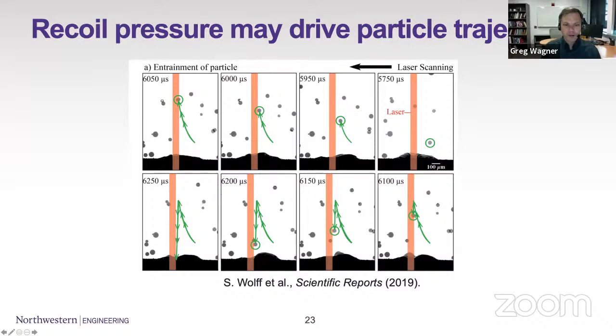One interesting phenomenon that was found in similar experiments was that sometimes powder particles are clearly not just blown away by the vapor plume, but once they get entrained in the laser itself, they seem to move in the direction of the laser toward the substrate. And there was some discussion over what's going on here. Why does this particle all of a sudden change directions as it moves into the laser?